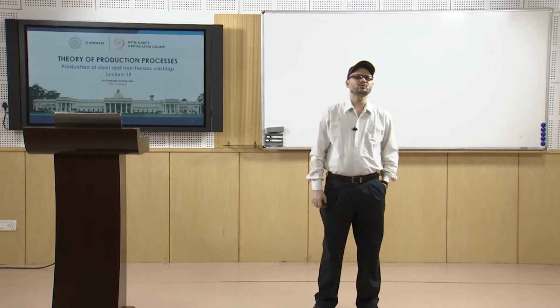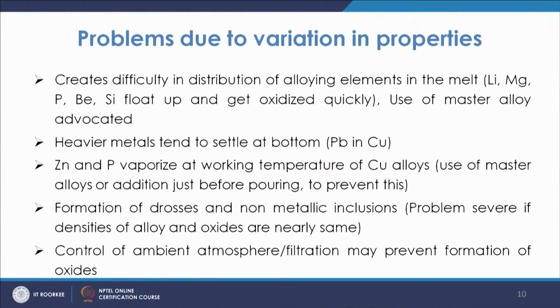Then there are problems due to variation in properties, like the difficulty in distribution of alloying elements in the melt. There are many elements like lithium, magnesium, phosphorus, beryllium, silicon, which float up and get oxidized quickly. For them we normally advocate the use of master alloys. This is one of the practices which is used.